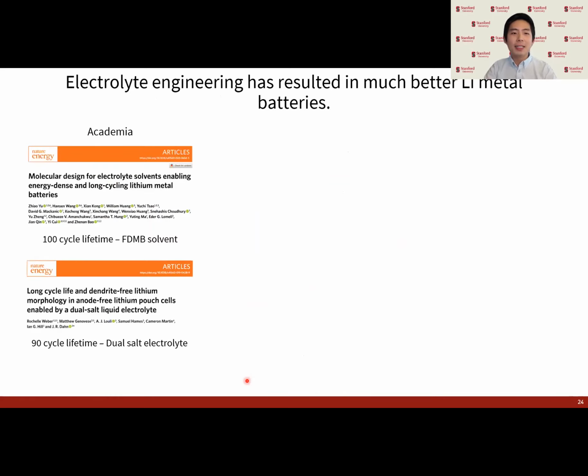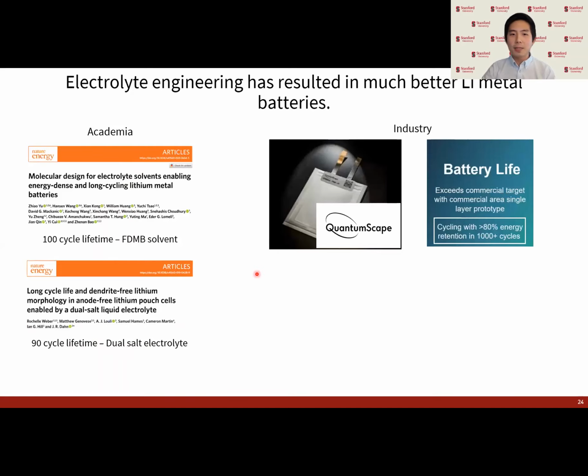So the previous electrolyte system of lithium metal with this FEC additive is an improved electrolyte system, but it is still fairly primitive for these lithium metal chemistries. Recently, what we've been seeing in academic literature is that new electrolyte formulations have increased the viability of these lithium metal batteries significantly, with groups here at Stanford developing new solvents, such as this FDMB solvent, which can enable 100 cycle lifetime in an industrial pouch cell format for a lithium metal battery. Or this work out of Dalhousie University, where a borinated dual salt electrolyte can enable 90 cycle lifetime. Outside of academia, startup companies like QuantumScape can show very impressive cycle lives as well, which makes lithium metal seem more viable in the near future.